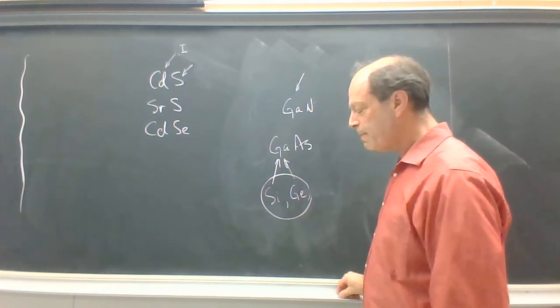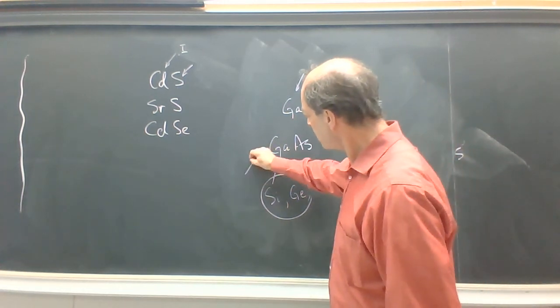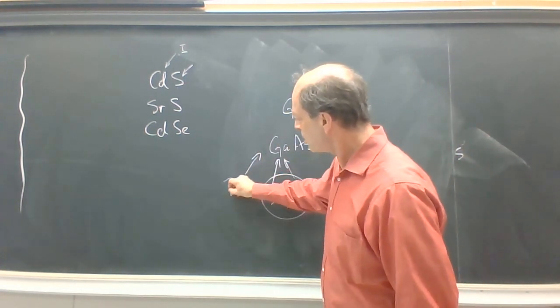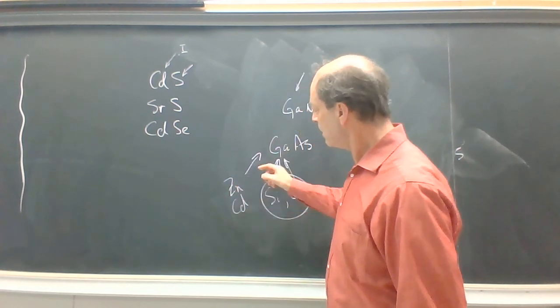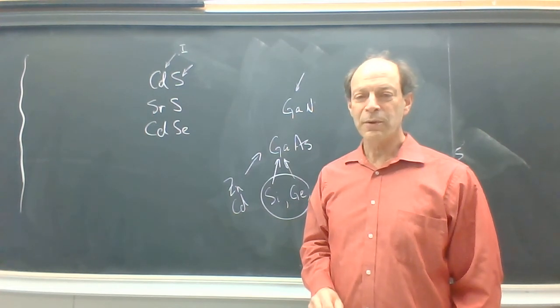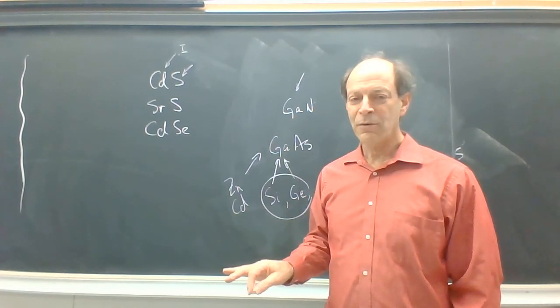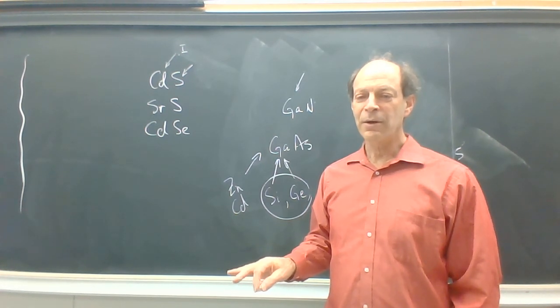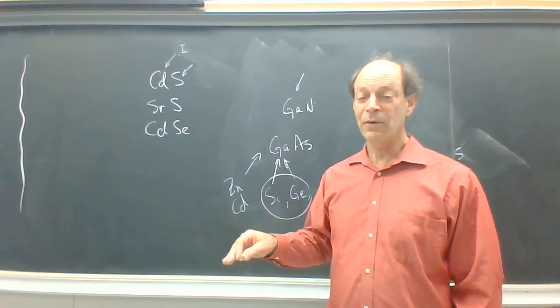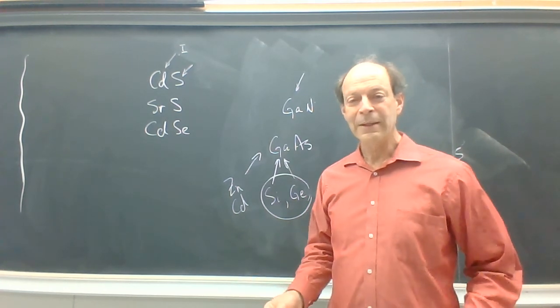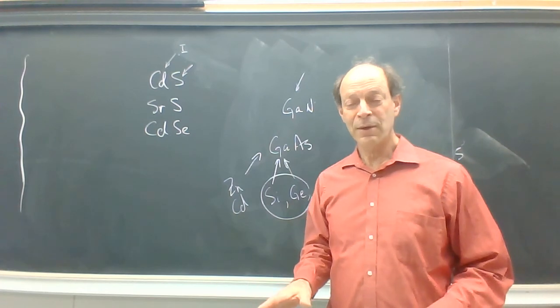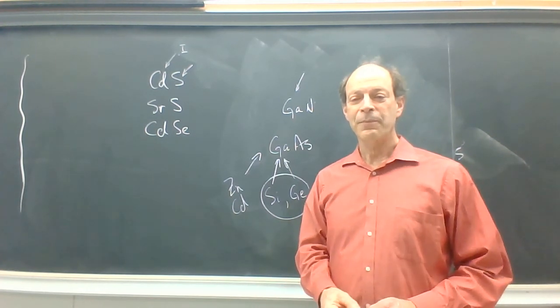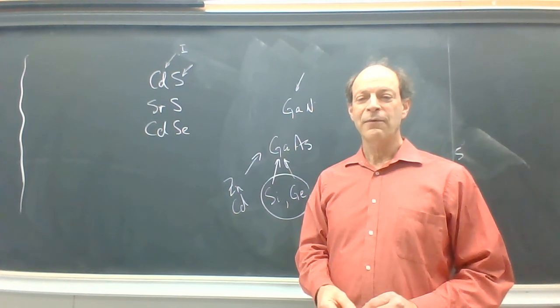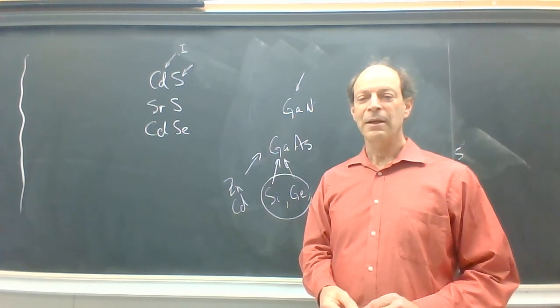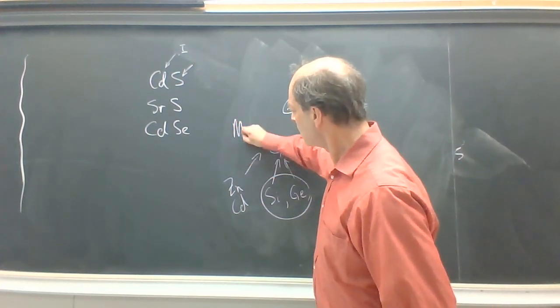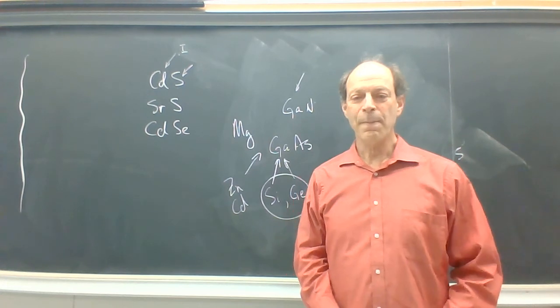The problem was in terms of P-type doping, the P-type dopants used to dope gallium arsenide really would be zinc or perhaps cadmium. And these 2+ dopants simply didn't work in gallium nitride. And that was a major barrier to gallium nitride use. In fact, that was one of the key reasons that other research groups around the world didn't take gallium nitride seriously, because they assumed it really couldn't be doped p-type. Well, one of the university professors in Japan found a way of doping it p-type, and the element he chose was magnesium. Now, magnesium is a group 2 element.